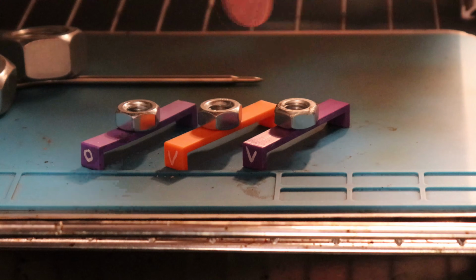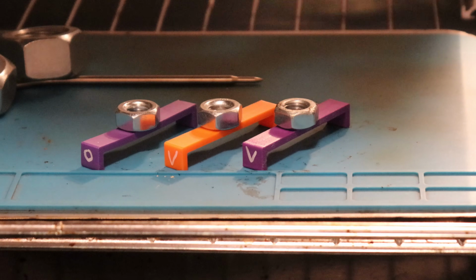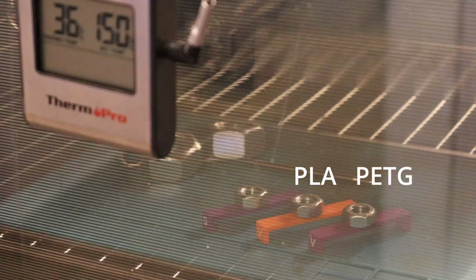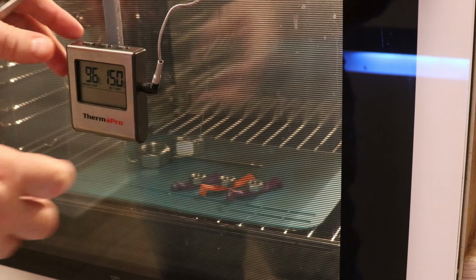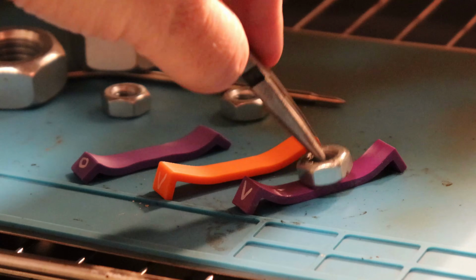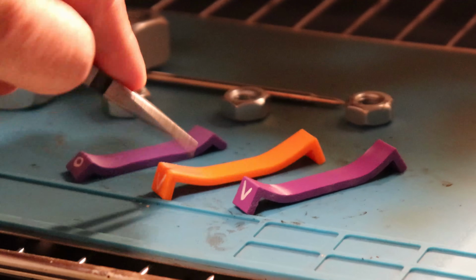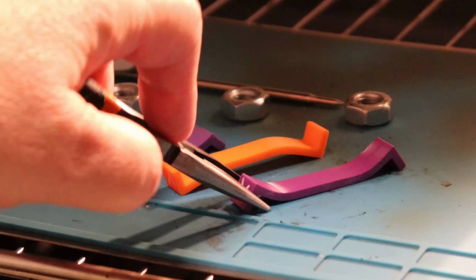Temperature test in the oven, and the two on the right side are the Voxel PLA and PETG filaments. I want to record the temperature of the first deformation, and no big surprises here. The PLA started at 57, PETG around 71 degrees Celsius. And I just check how hard they are. And more or less this is typical for these materials.